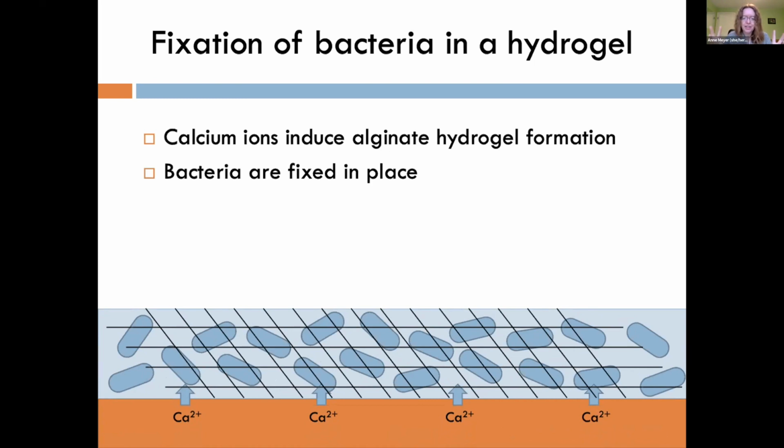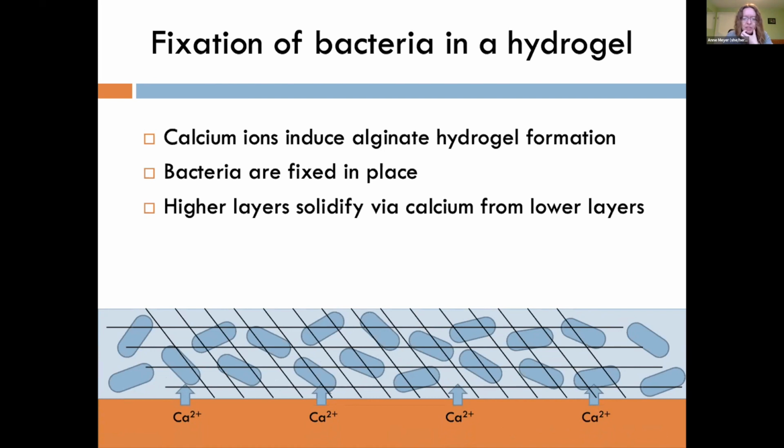And the bacteria are trapped inside the alginate matrix because the pore size is smaller compared to the size of the bacteria. So it's more or less trapped in place over time. The great thing about a hydrogel is that it's mostly water. It's like 95-ish% water, which means that, first of all, the nutrients in the agar can continue to diffuse in and feed the bacteria after printing.